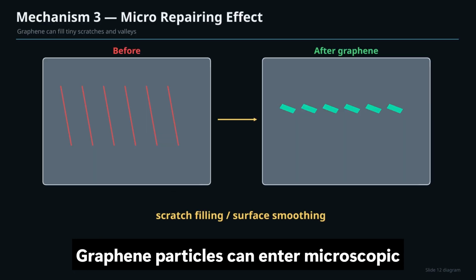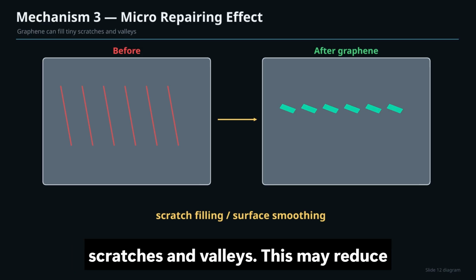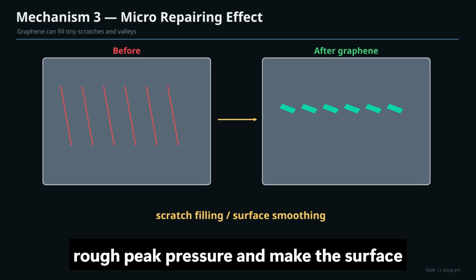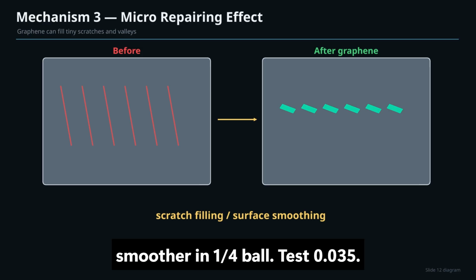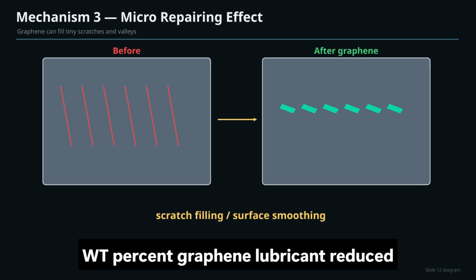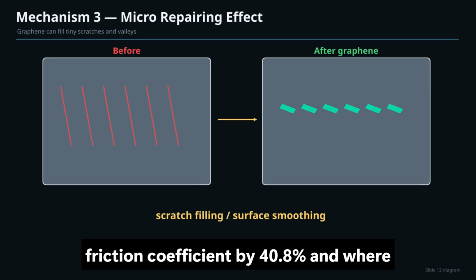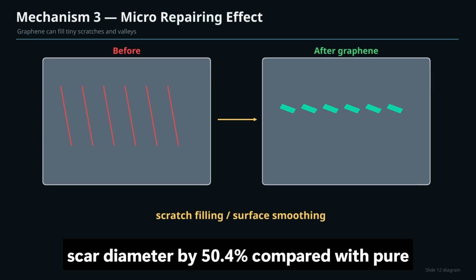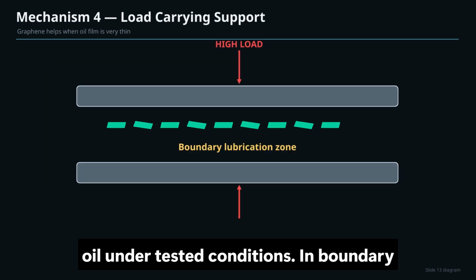Graphene particles can enter microscopic scratches and valleys. This may reduce rough peak pressure and make the surface smoother. In one 4-ball test, 0.035 Wt% graphene lubricant reduced friction coefficient by 40.8% and wear scar diameter by 50.4% compared with pure oil under tested conditions.